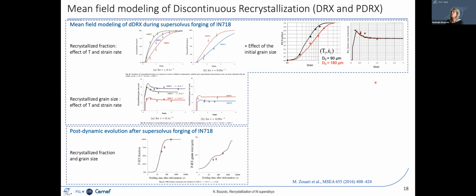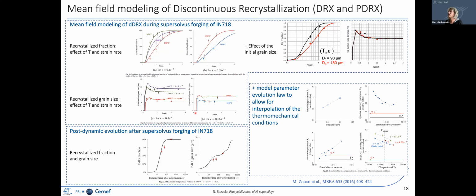You can also, with the same equations, describe what's going on after hot deformation, so the post-dynamic evolution. This is what is shown here. And in addition, if you calibrate the model, if you identify the parameter values for different thermomechanical conditions, then you can also interpolate the model parameter values so that in the end you are able to model